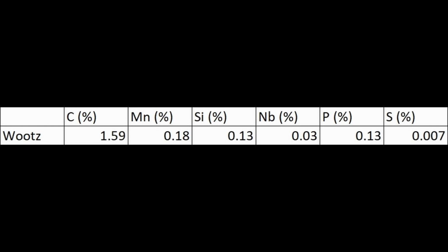We also added a little bit of manganese for hardenability, 0.18%, because we needed some hardenability. Hardenability is not how hard the steel can get, but how slowly we can cool the steel and it's still fully hardened. So you can have a high hardenability, low carbon steel that doesn't get very hard, but you can cool it in air and it still gets as hard as it will get. Spencer actually sent me some steel originally that had little or no manganese, and I could not harden it in oil at all. And I actually still had difficulty hardening this steel even with 0.18% manganese, which is not particularly high.